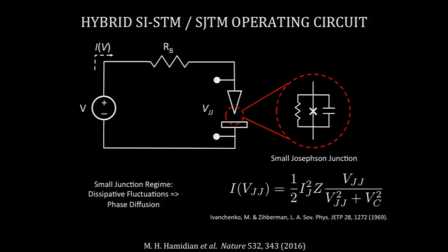This is the circuit for this scanned Josephson microscope. Here's your voltage source that we're going to turn into a current source by putting a resistor here. This is your tip, and this is your sample. And now this is a Josephson junction. We can model it as this circuit element. It turns out because the junction is so small, it's a nanometer-sized junction, it's no longer a coherent Josephson junction. There are some very smart people in Russia who worked out the characteristics of a nanoscale Josephson junction, which works in what we call a phase diffusion regime, where as you inject the Cooper pair, its energy changes a little bit and you can emit a photon, for example. They found that in that case, the IV characteristics are not directly proportional to the critical current, but to the square of the critical current.